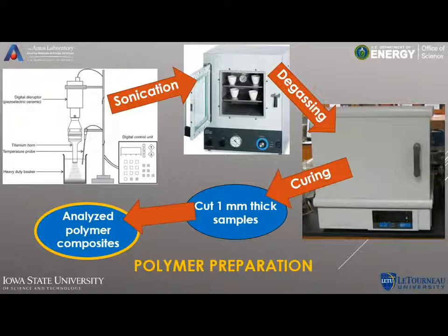The polymerization process for these composites started with first mixing the materials together, and that was done by sonication. We started out with the monomer material, which is basically the plastic in liquid form. It's not been polymerized. You've got a bunch of small molecules. And then we added the filler material, the nanorods, and to that we also added the catalyst for the polymerization. And so we would mix these up with sonication, which functions by emitting high-frequency sound into the liquid material. And that actually works to stir the material around. And you'll see lots of little bubbles rising to the surface just because things are being stirred so well.